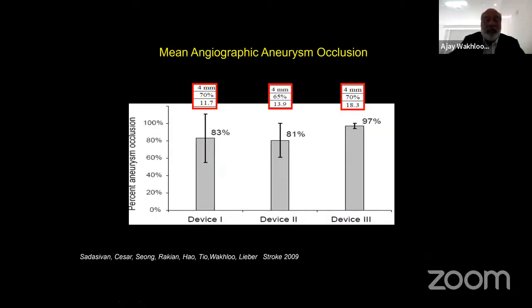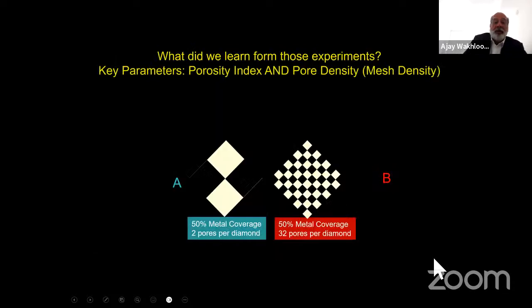So we introduced that terminology of porosity. And then when you look at the mean angiographic occlusion, you will recognize that the device with the higher porosity as compared to the lower one had a higher occlusion, but the main driving force was the mesh density, or pore density. In other words, if you have the same device with less pores per square millimeter, the impact on the mean angiographic occlusion was lower.